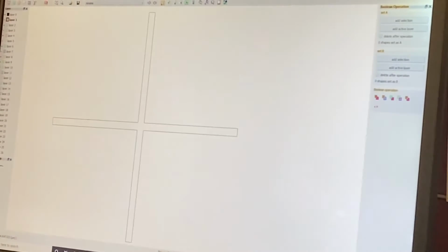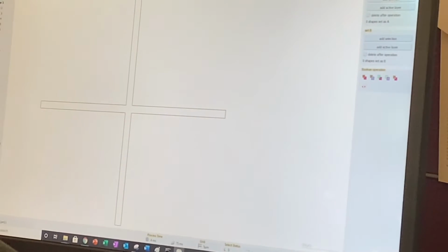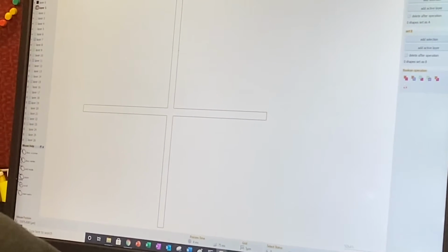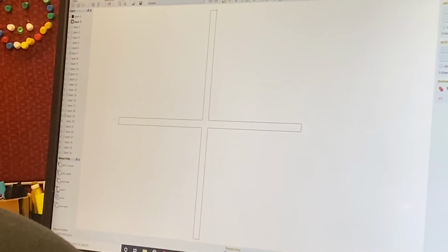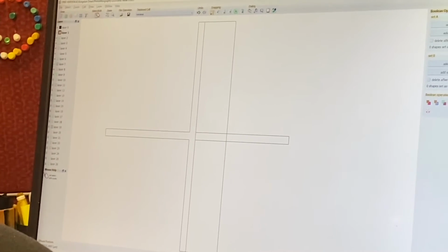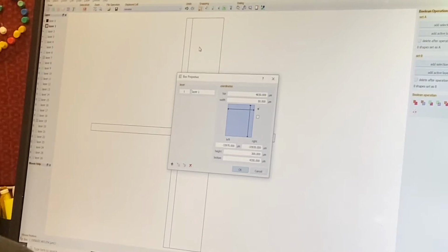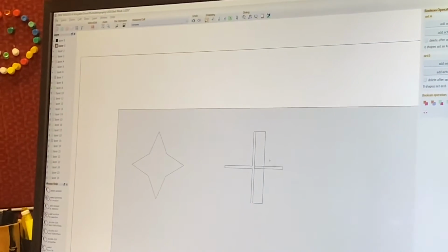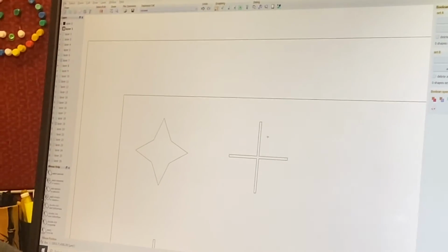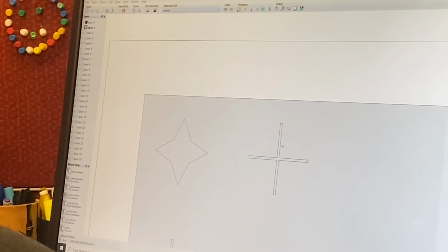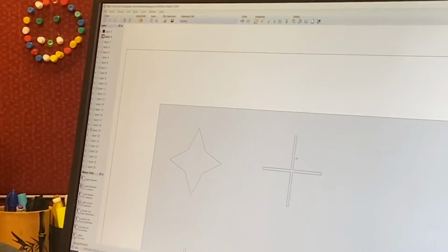So you can see my alignment marker is 10 micrometers wide, because each dot here is 5 micrometers. So this is 10 micrometers wide, 10 micrometers tall here. And then the height of my thing is 50 micrometers. Oh no, sorry, 300 micrometers. Yeah, so I made it 300 micrometers tall, but only 10 micrometers wide. You may not need to make it that tall, you can make it shorter if you want, but 10 micrometers is how thick it should be.